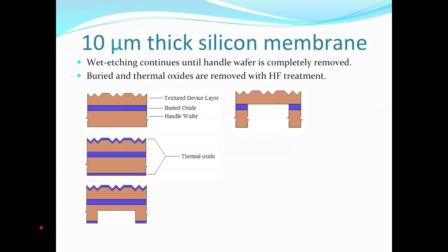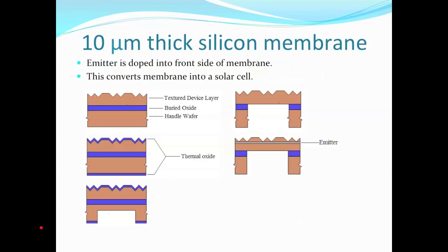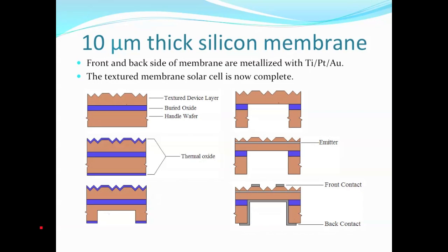Once the handle wafer's been removed, then we remove the thermal oxide and the buried oxide using an HF dip. An emitter can then be doped into the front surface, and then we can contact the front and back to turn this into a solar cell.